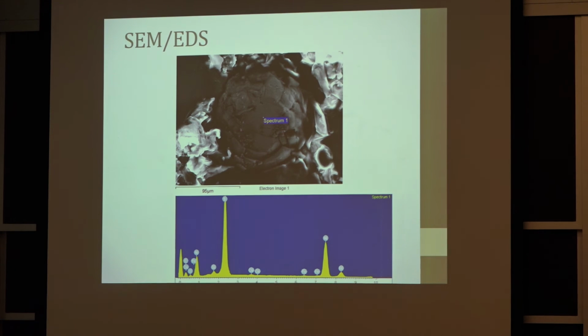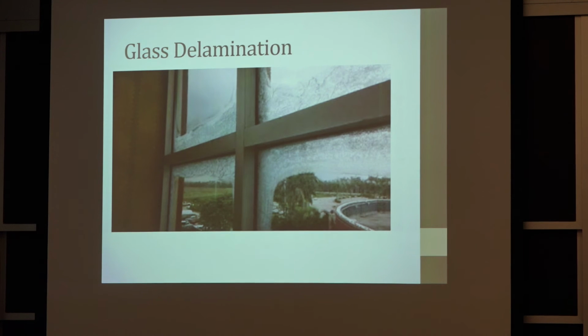So what you do is you put the glass in the scanning electron microscope. In this case, you have two types of microscopes. Some of the SEMs, you don't need to put any coating, and they can do non-metallics. In this case, some gold was sputtered on the surface, so in the SEM you can actually see what we're looking at. This is the image in the SEM under higher magnification, and you see the spherical appearance, and then we did EDS, and you see you have some peaks for nickel and some peaks for sulfur to confirm.